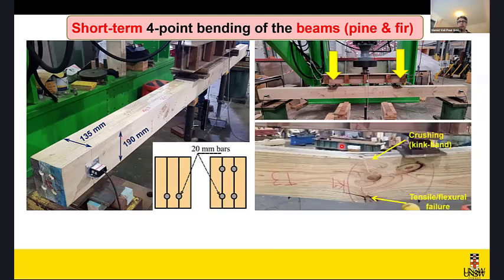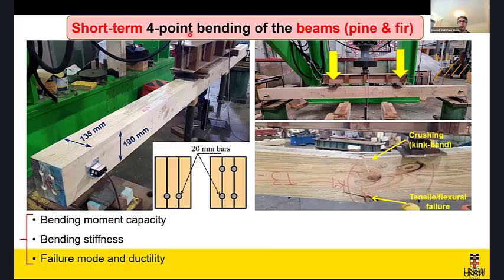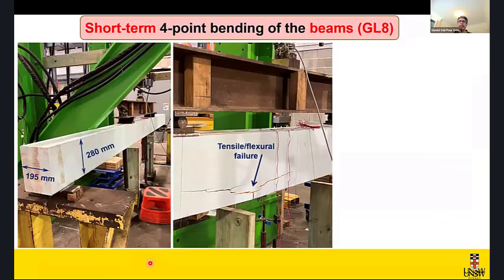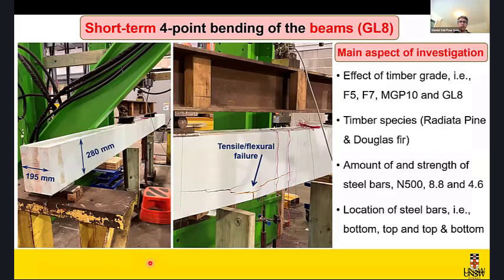And that's what the failure mode looks like when we have reinforcement. You see crushing or development of a kink band in timber, and tensile flexural failure in the tensile zone of the beam. In this case, basically it's initiated from the location of the nuts. The main goal was to establish the bending moment capacity, bending stiffness, failure modes, and ductility when we have this reinforcement in the system. Again, another example of a four-point bending.